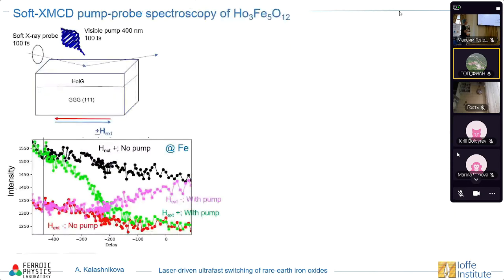So now let's do the experiment. Let's use a femtosecond laser pulse to excite our material. And let's use X-ray pulses, but they are very short, therefore they have really low intensity. So these experiments really take a lot of time, but we do pump-probe with this soft X-ray probe. And this is a typical experiment. Sorry, they are quite noisy, but still I think we can see important effects here.